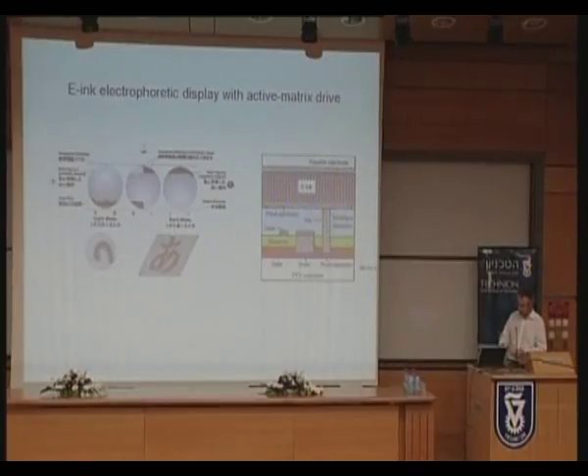And the display that we've gone for is an electronic paper display. We're making use of a display effect that has been pushed very hard by a company in Boston called E-Ink. That's electrophoresis, where they've produced a foil with liquid-containing capsules with black and white pigment, and one or the other is pulled up to the top surface, depending on the applied voltage. So it looks like black ink on white paper, more or less. Very appealing to look at. And it's flexible. In order to turn it into a useful display, it needs a matrix of transistors to set the voltage right at every point on the display. And what we're doing is making that matrix with our plastic transistors.